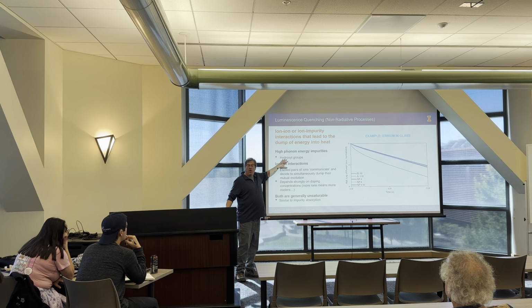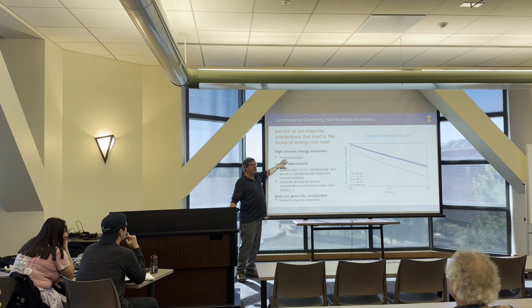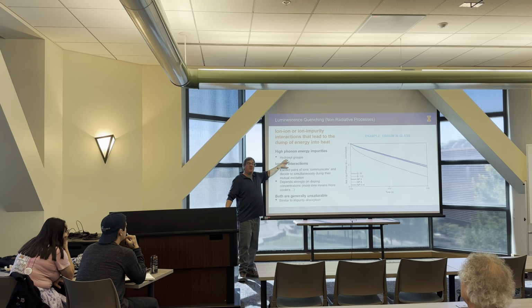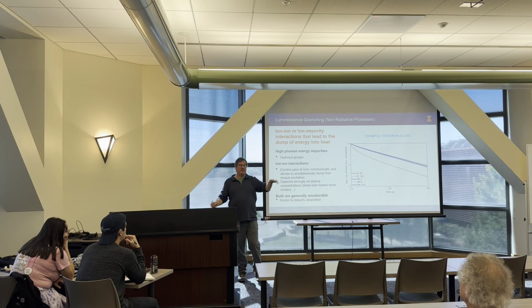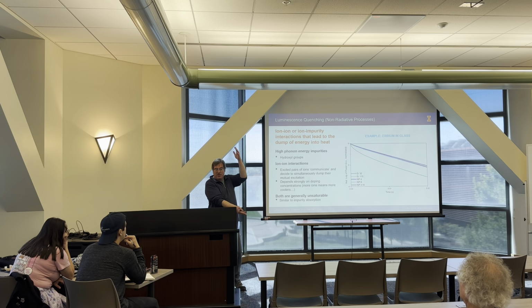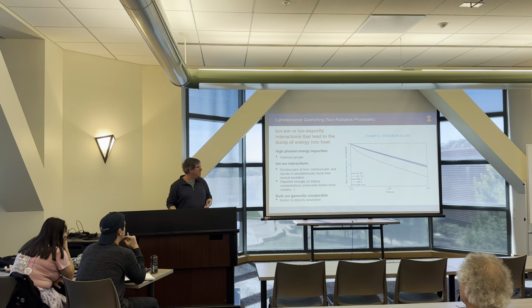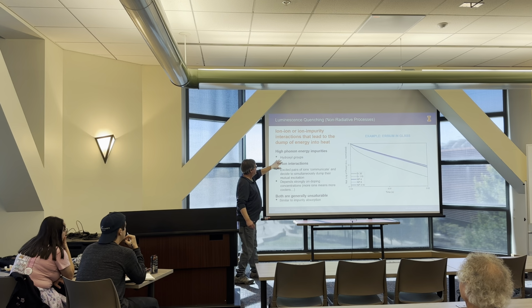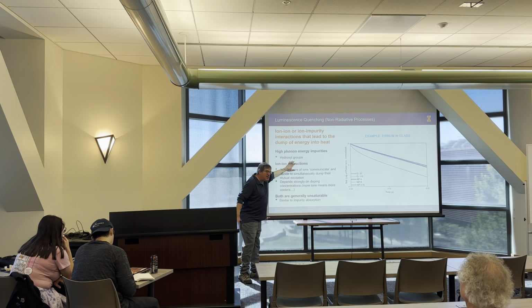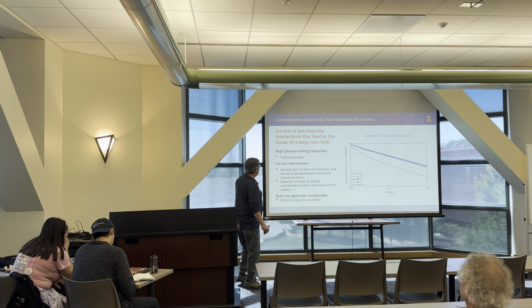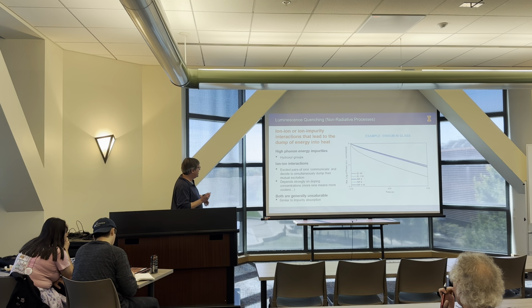Hydroxyl, for instance, OH, that you might find in glasses, has a phonon energy of about 4,000 inverse centimeters, and that's already only about 2 phonons to traverse the energy gap for ytterbium. So this is a huge problem. A lot of work goes into removing this from the solids that might go into cooling. Obviously, where you don't have oxygen, this doesn't matter.